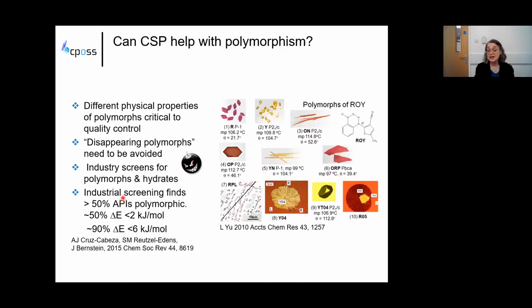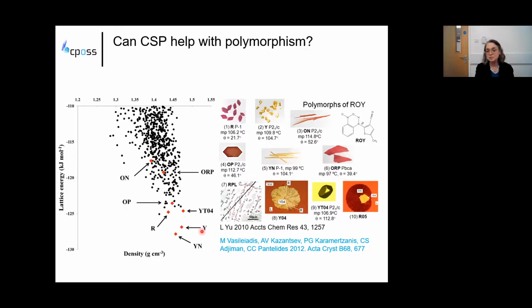And in industry, they reckon that at least half of the molecules are polymorphic, with often very small energy differences between the different crystal structures. So this is an example of the crystal structure prediction study done by our colleagues at Imperial College, whose codes we beta test. And the known polymorphs of Roy are in red diamonds. And you can see, yes, they're coming out of the lowest structure, but there are quite a lot of polymorphs where there wasn't a structure. And you can see the black dots means there are an awful lot of candidates for these structures.